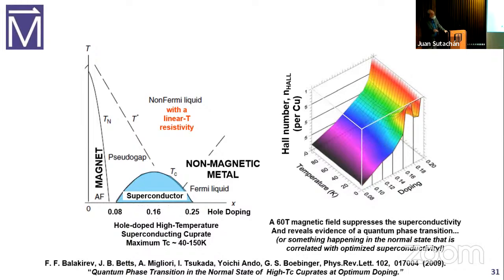There's a peak in the number of carriers, and it's right near, in this case it's at 0.17, right near the situation where the superconductivity is best. So why is there something happening in the non-superconducting state right at the same doping where the superconductivity is best? This is either a clue to what's causing high temperature superconductivity, or nature is being really cruel and giving us a coincidence that has no physical meaning.